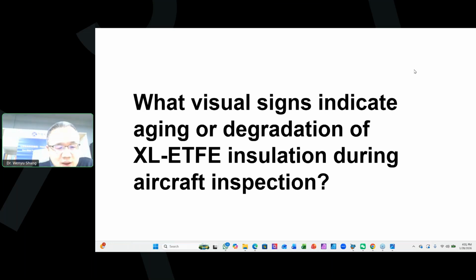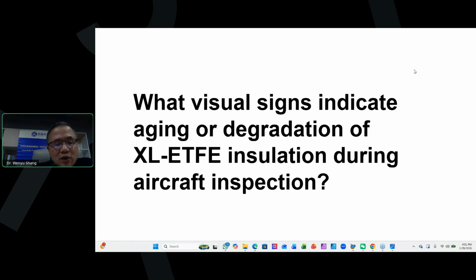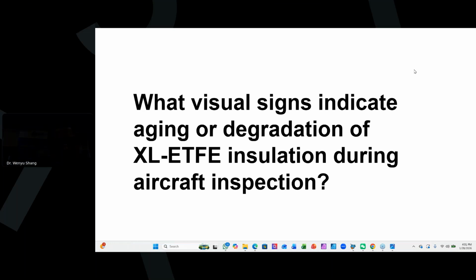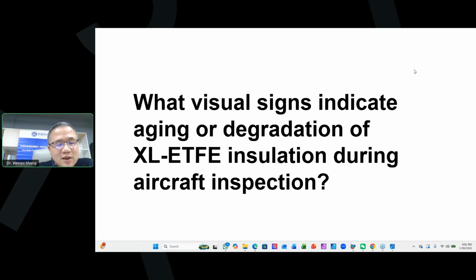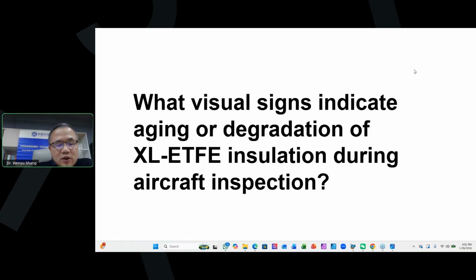Number two is the color. So for the part of the cable that needs to sustain very high temperature, you can imagine that for the whole cable connecting the control center to the engine or to the sensor, not the whole cable needs to sustain 200 degrees C or 260 degrees C all the time. So it's only part of it working under such high temperature. This part of the cable will over time have its own color change because of the exposure to the heat. So if the color changes beyond a certain range, it's a very direct indicator that the cable is going to fail in a certain time window.